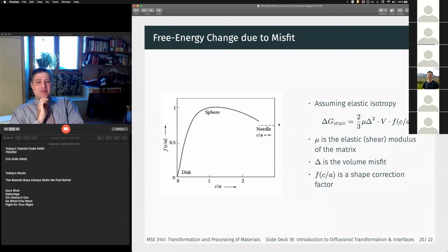But we have a free energy change due to this misfit, right? So we have a Gibbs free energy associated with the incoherency strain. That's going to be related to the elastic modulus, the shear modulus in this case, and the volume misfit, right? So we have a shear modulus times the misfit strain times the volume, and then this shape correction factor.